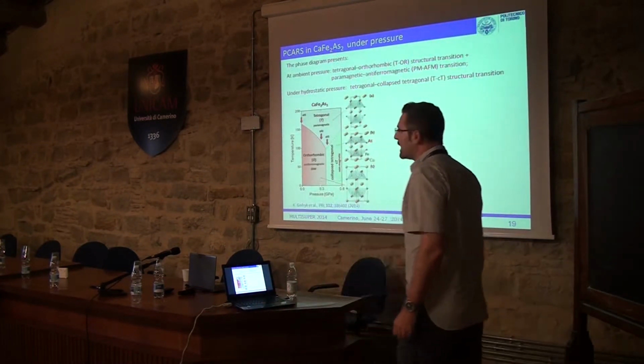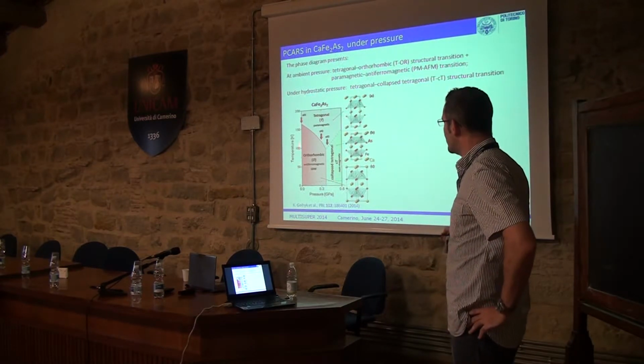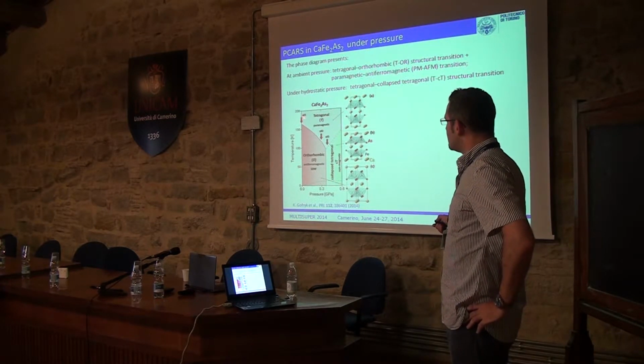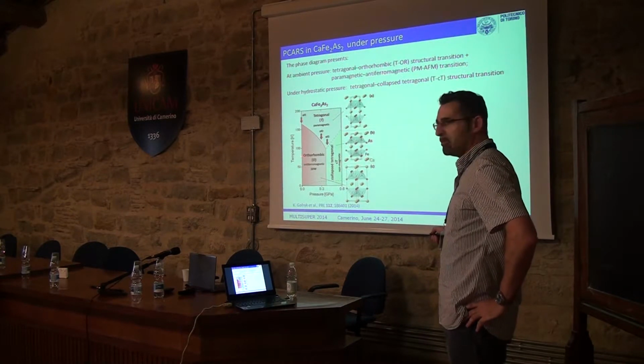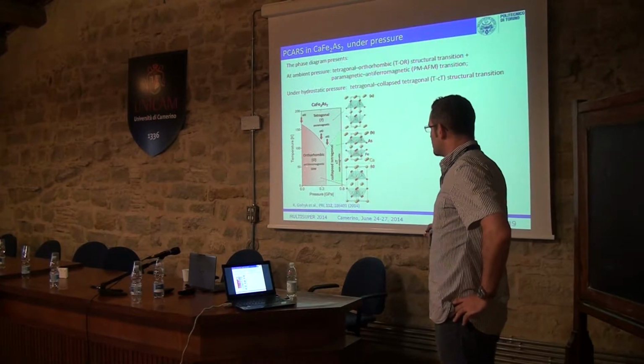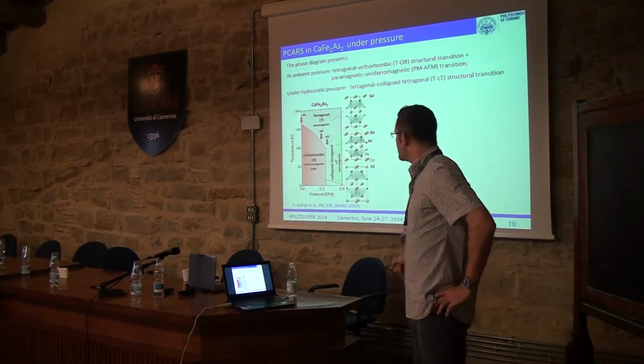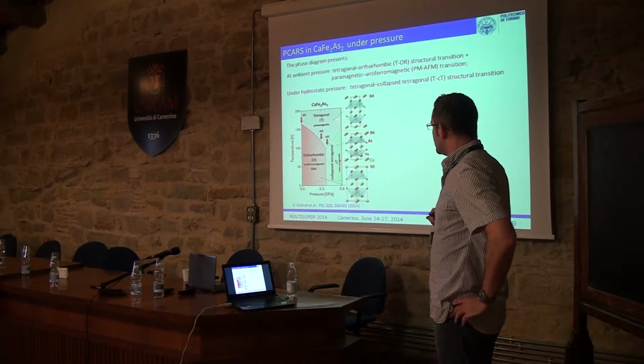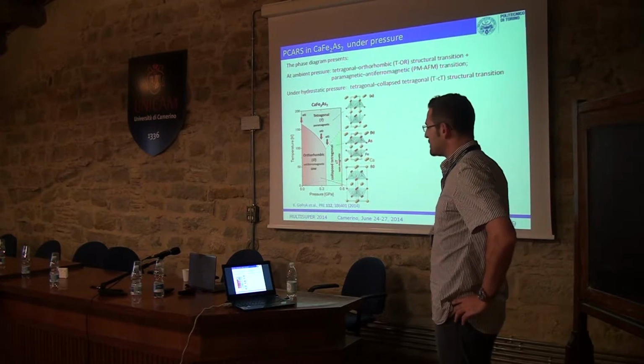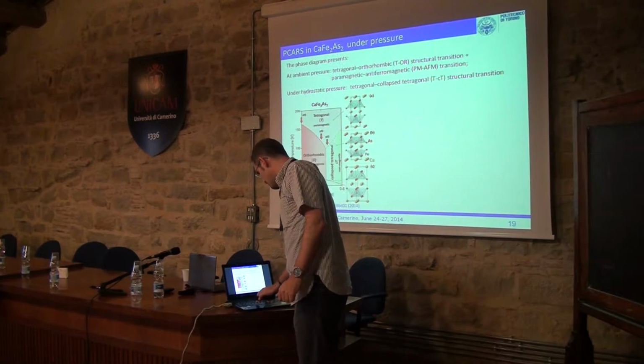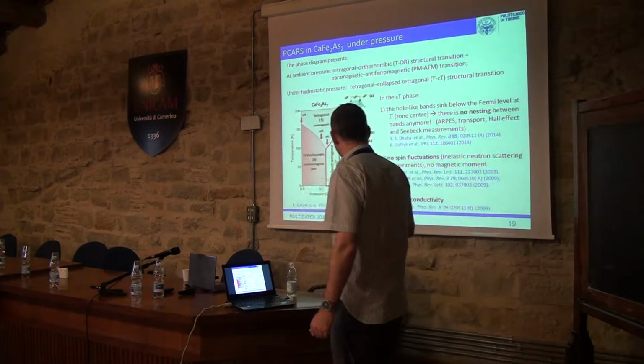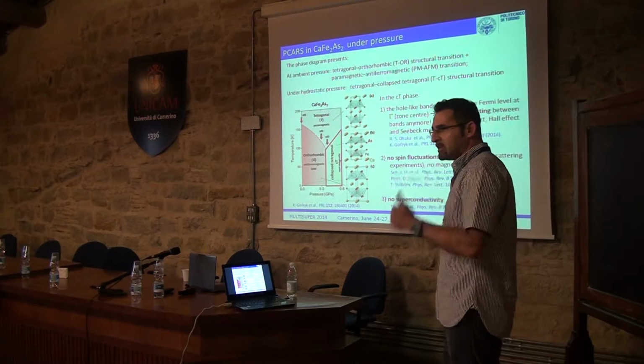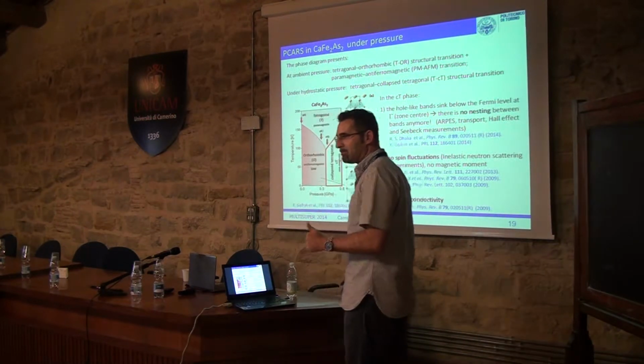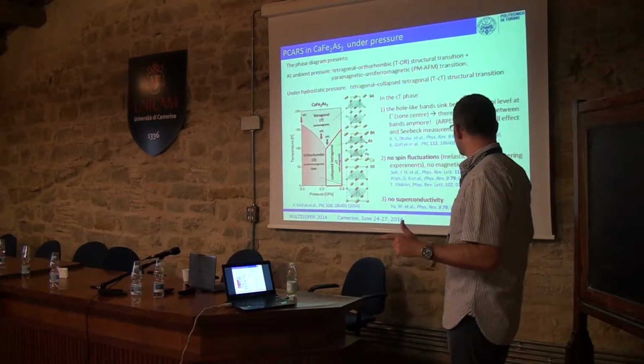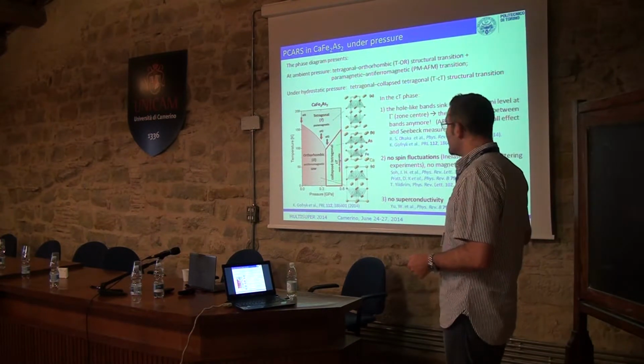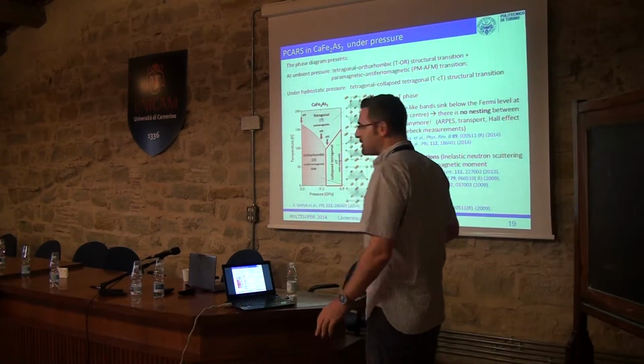Well, let's go now to calcium 122 under pressure. This is the phase diagram. At ambient pressure, calcium 122 has a tetragonal to orthorhombic phase transition, which is also associated with the onset of the antiferromagnetic phase. In hydrostatic pressure, it shows a tetragonal to collapsed tetragonal phase, the one already described by Dr. Paglione. In this phase, as already said, there is no hole-like Fermi surface around gamma. There are no spin fluctuations. This has been proved experimentally and also calculated. The magnetic moment is completely quenched, and there is no superconductivity.